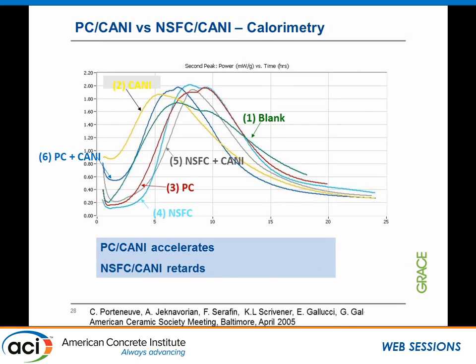So in here, we are looking at the calorimetry of these curves. So the first one, if you can follow me, is this green one. This is the blank, a very, very typical blank mix design. With calcium nitrite, which is an accelerator, you can see the yellow, it gives you the acceleration, no problem. When we add the polycarboxylate, it does give retardation from the blank, and so does naphthalene sulfonate. Okay, not too much, it's still in a good way.